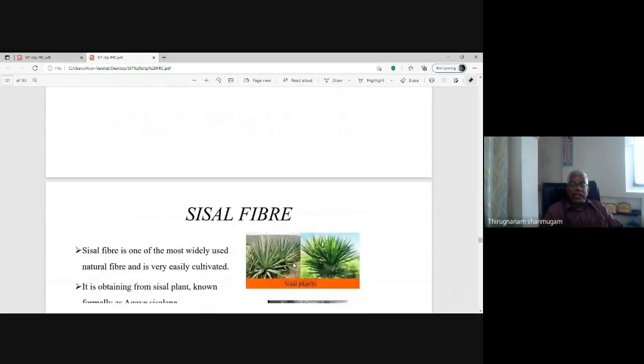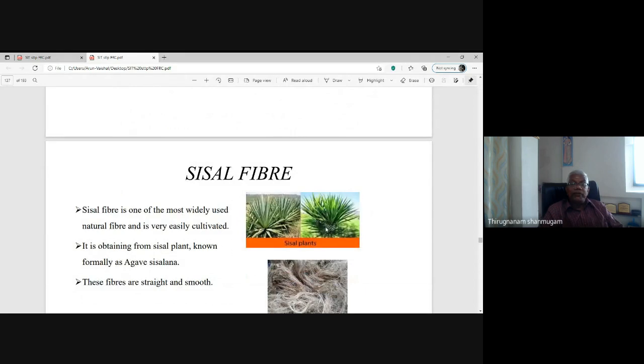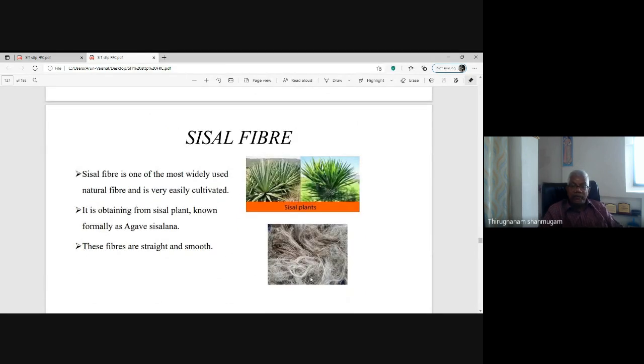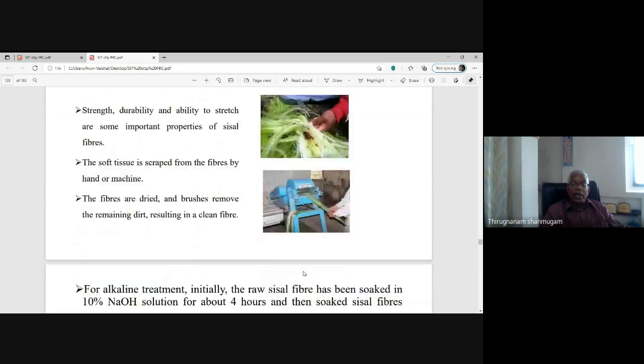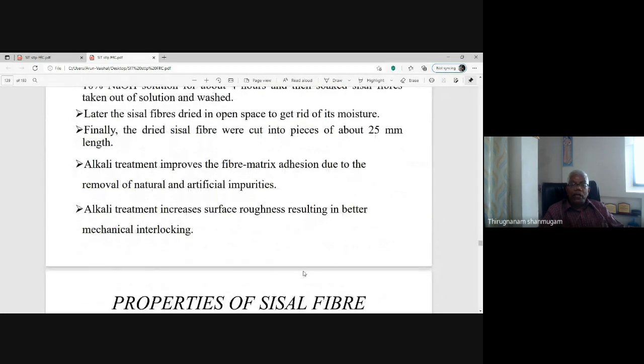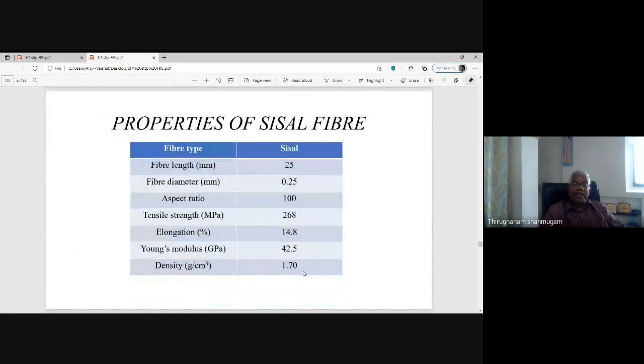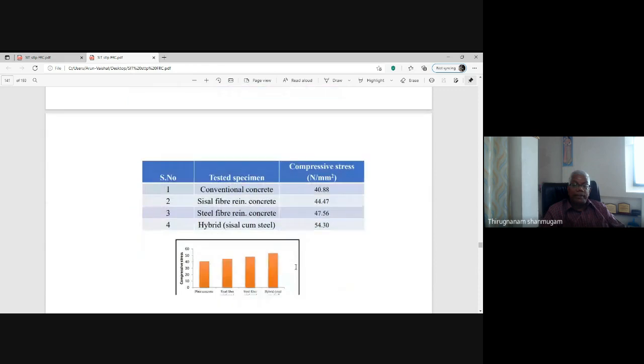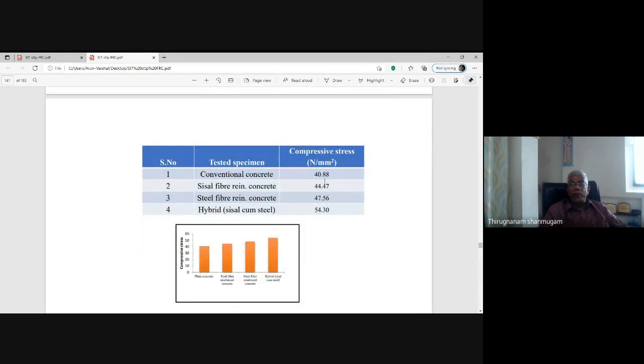Similarly, sisal fiber is here, sisal fiber and coir fiber. These fibers are manufactured similar to these banana fibers, and alkali treatment is used for improving the properties of the fiber. These are the properties of the fiber: 25 mm length, diameter 0.25 mm, aspect ratio 100, tensile strength very low, 268 Newton per mm square, 15% elongation, Young's modulus 42 gigapascal, density 1.7 gram per cc.